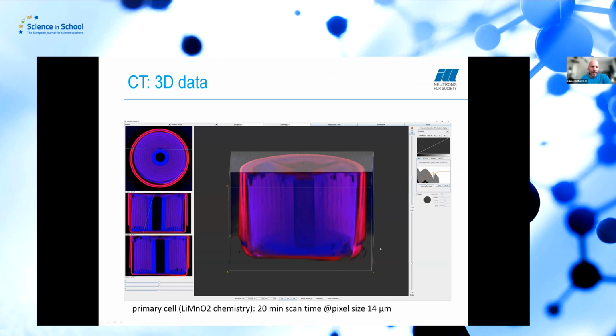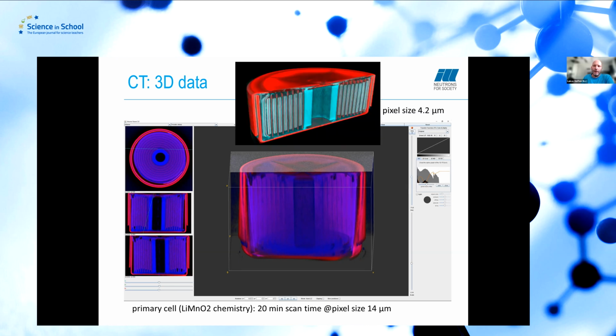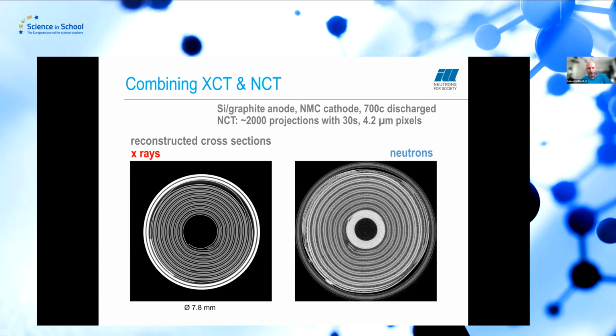Okay, I show you now some examples, also here again coin cell batteries that you can have a look at, and look at the microstructure of the cathode and anode materials. So here we can go with very high spatial resolution, for instance, a pixel size in the order of 4.2 microns with long scans. That's the inconvenience. So it is not so much adapted to operando imaging during discharge or charging cycles. But you can then do studies of the capacity fade during aging of batteries. So if you charge them 100 times or 300 times, what happens then with the cathode and anode materials?